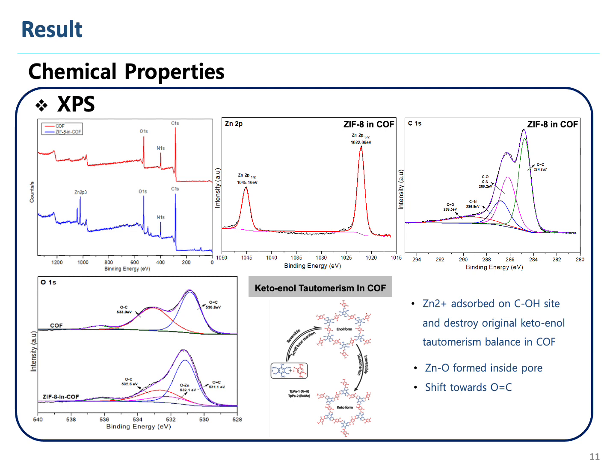Most importantly, we can observe a shift in the peak from the oxygen high-resolution XPS, in which a new zinc oxide peak is observed inside ZIF-8 in COF. We can know that this shift happened because zinc is absorbed on the C-OH site and destroys the original keto-enol tautomerism balance in COF. And therefore, the zinc oxide is formed inside the pore and the COF shifts towards the C=O, which is a more stable structure of COF. And from here, we can conclude that there is a successful synthesis of ZIF-8 in COF structure.